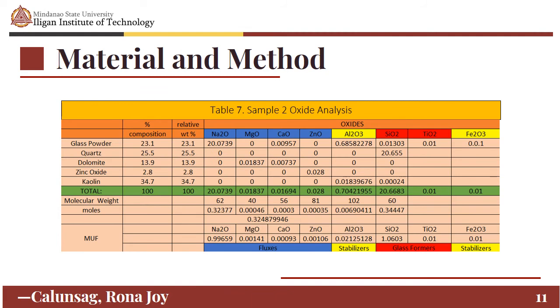Table 7 shows the sample 2 oxide analysis, which was also fired at 1250 degrees Celsius. This shows the fluxes, the stabilizers, and also the glass formers. Na2O has 0.99659, MgO 0.00141, CaO 0.00093, ZnO 0.00106. For the stabilizers, the Al2O3 has 0.02125 and the Fe2O3 0.01. For the glass formers, SiO2 has 1.0603 and the TiO2 has 0.01.